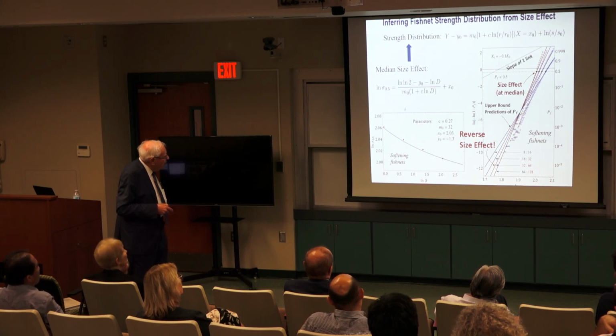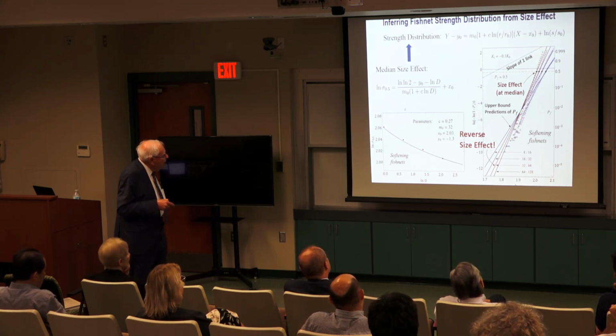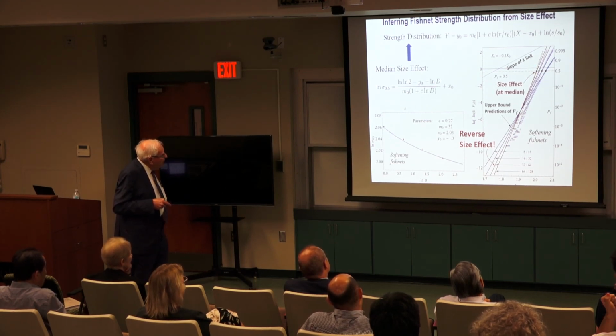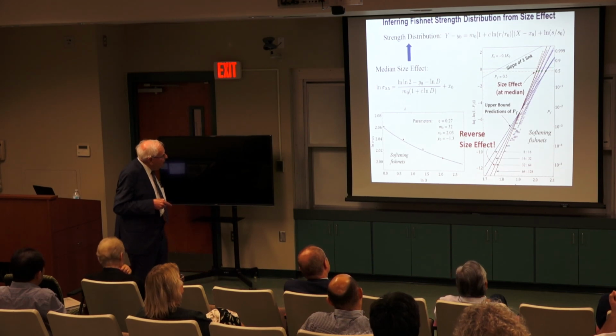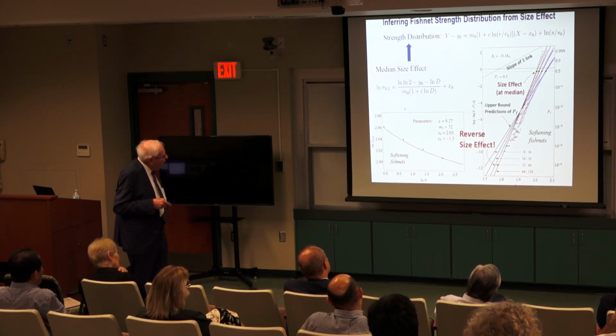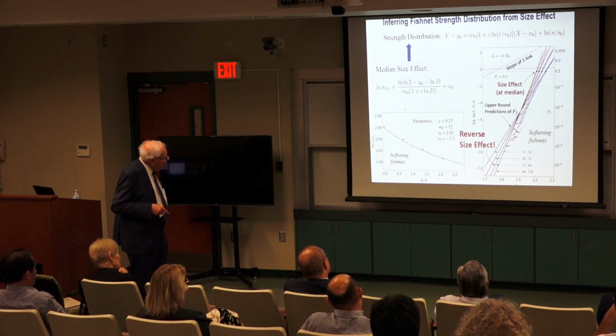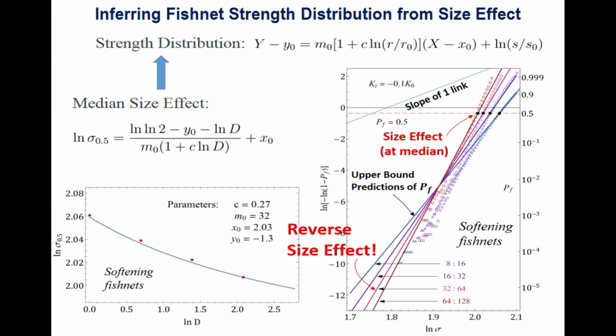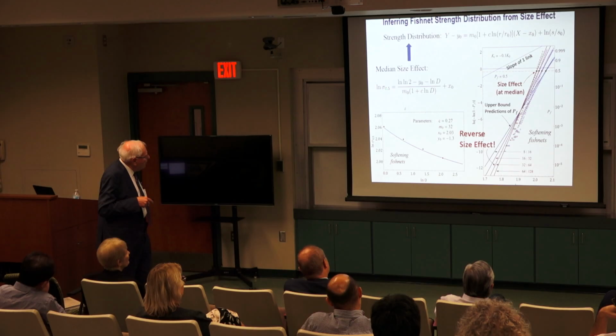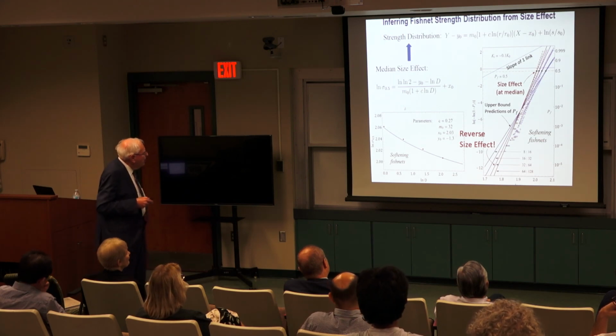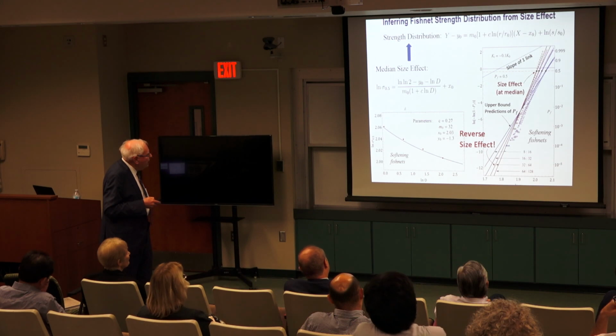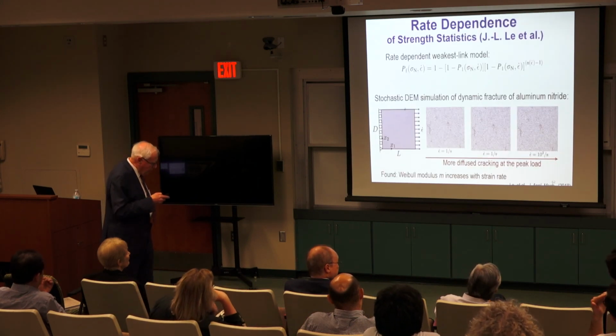Still there is an intersection point, but it goes to a low probability, not being here, somewhere low. But it can happen, and probably often happens, that positive size effect in the mean, or this is median actually, you see the structure is getting weaker as it becomes larger. Changes at 10 power minus 6, which would be, wait a minute, this is not probability scale, it's about here. We can have opposite size effect in the tail. So structure which has a significant variation gets opposite behavior. And we can get this way, we can approximate a reasonably good formula for the mean, for the median, sigma 0.5. It would be better to do mean, where mean is actually much harder, but they are close enough. So this is our latest work, which is just being published. We just finished a paper on this.